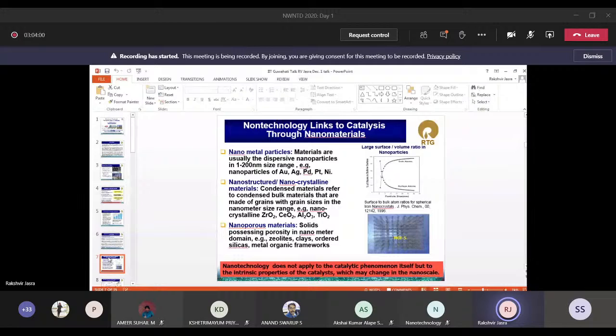Second is the nanostructured, nanocrystalline material. Most of the time we use metal oxides as a support for these nanoparticles. Nanoparticles are supported on metal oxide supports like zirconia, alumina, silica, titania or ceria, which I have shown here. Now these materials also you can produce in a nanocrystalline form, not a bulk material. The grain size can be controlled. That also helps in a big way to improve the activity of the particular catalyst made from this support as well as the nanoparticle.